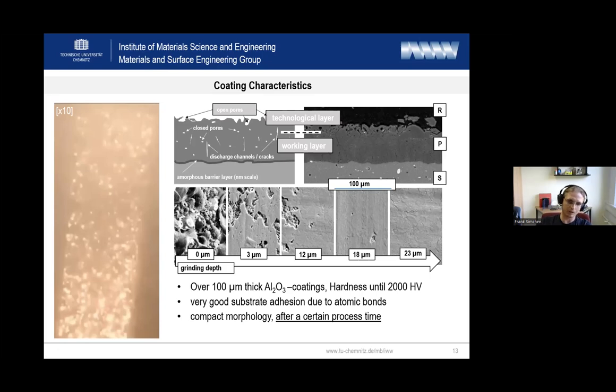So, these coatings can be thicker than 100 micrometers, and we can achieve hardnesses of around 2000 Vickers. So this you will not get by conventional anodizing. We have a very good substrate bonding due to atomic bonds. So this oxide is connected to the substrate really by atomic bonds.